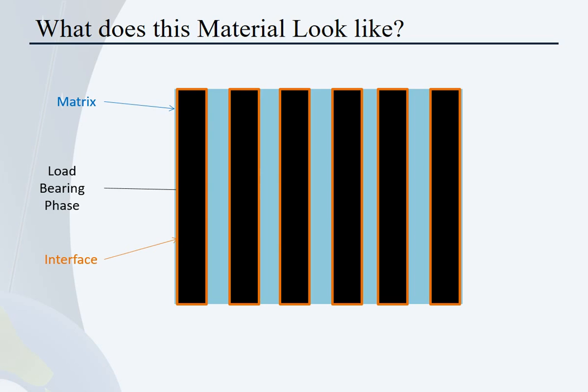Most likely, this means chemical bonds. So we're going to do a little bit of damage to our nanotubes, carbon, boron nitride, whichever they are. And this will cause each individual tube to be a little bit weaker. But as we've seen, the individual tubes are not the problem right now. They're pretty close to our expected maximum for tensile strength per weight. We can afford to give up a little bit of that strength in order to get the macro scale material up from that aramid line into the area that we need it to be for our space elevator. And that's where this interface comes in. We're not going to break every bond on the surface, just a few, just enough to couple the matrix and the load-bearing phase, which will lead to the load-bearing phase elements being coupled together.